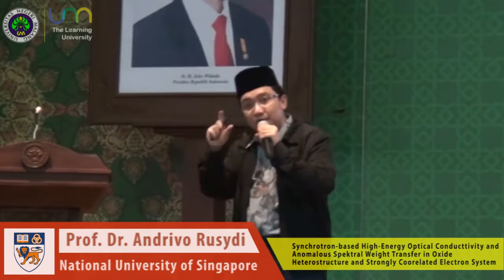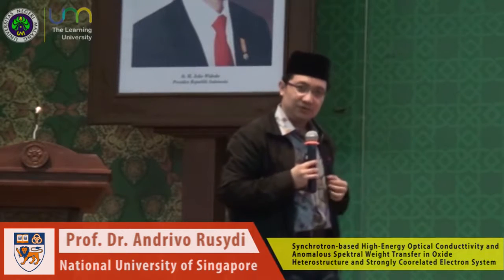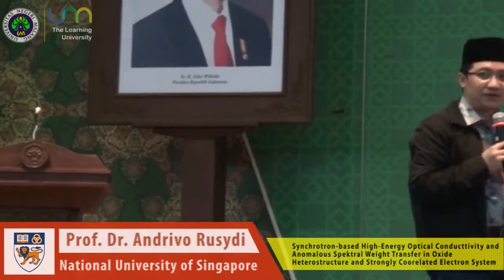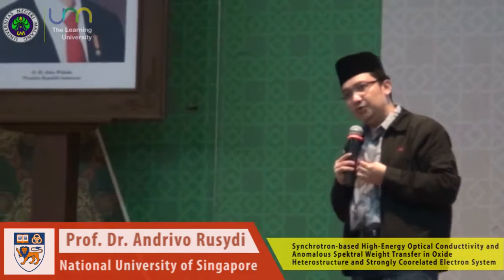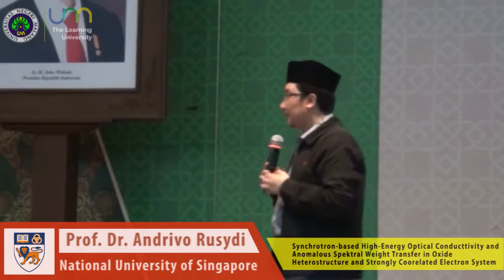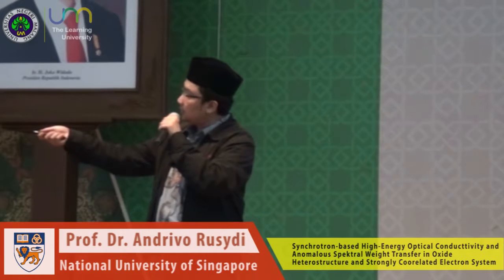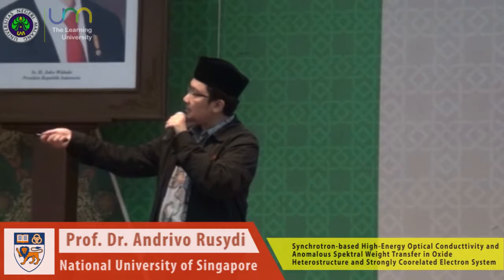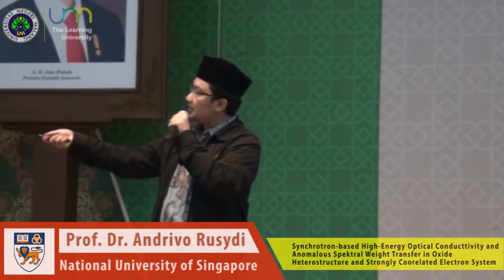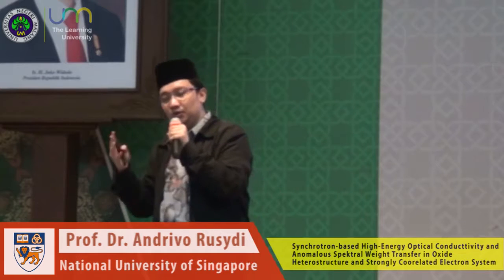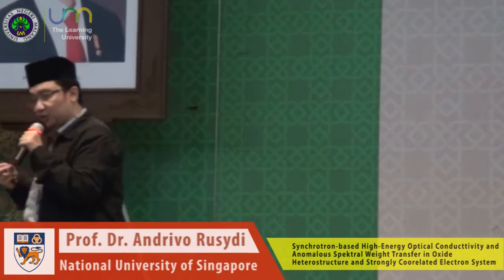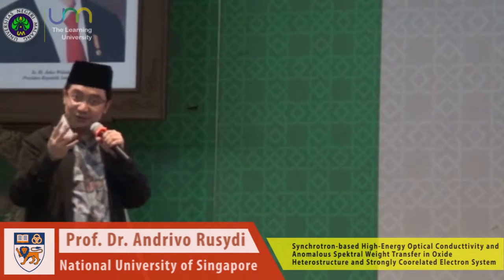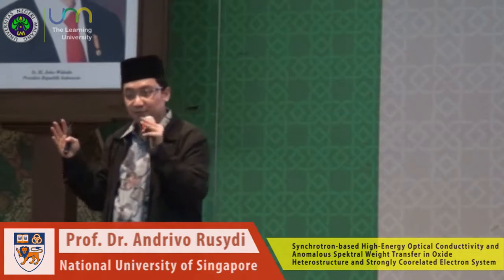And then we calculate the optical conductivity and the dielectric functions, real part and imaginary part, but this time you explicitly include electron-electron and electron-hole interactions through, for instance, GW Bethe-Salpeter equations. You can do that. Now you can see the red and the black. The black was assumed to have no exciton at all, no electron-electron-hole interaction in STO. That was our knowledge in the past for many, many years.